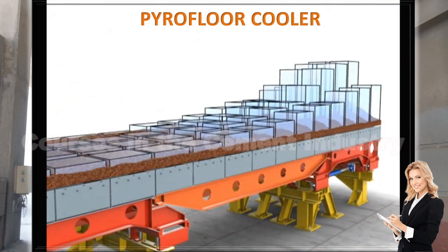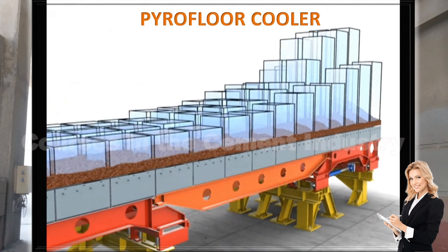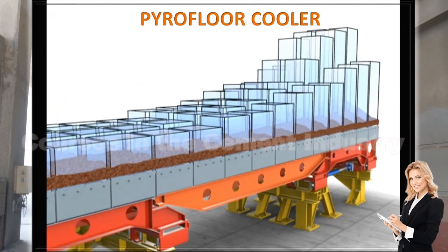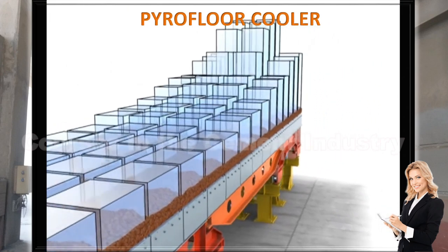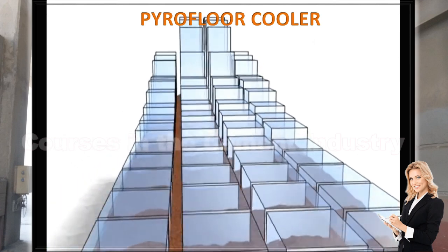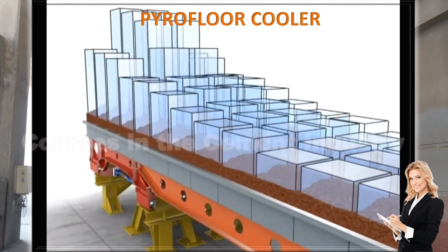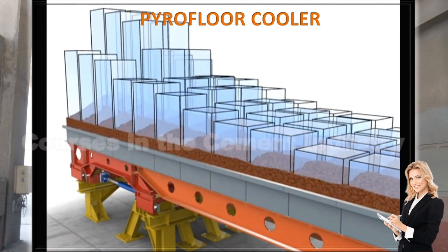The non-uniform height and temperature distribution of the clinker bed can now be met with a precisely balanced air supply to any spot of the grate without the usual complicated ductwork and flaps. The aeration sections created in the Pyrofloor cooler are small enough to keep up their controlled aeration even if a neighboring section should be subject to temporary failure.